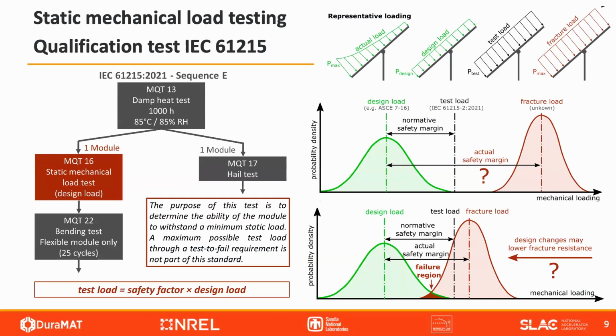And we do have what's called qualification testing, which is specified in the standard here. And there is one sequence in there that looks at static mechanical load testing. But it only tests up to a certain test load that I've showed you before. And this test load got smaller and smaller and smaller over the years. And so if you look at the actual load, let's say this is wind or snow, then you usually end up with some kind of distribution, and you can derive a design load for a certain site at a certain location around the world. And then we test up to the test load, and if the module succeeds this test, then we can get the normative safety factor.